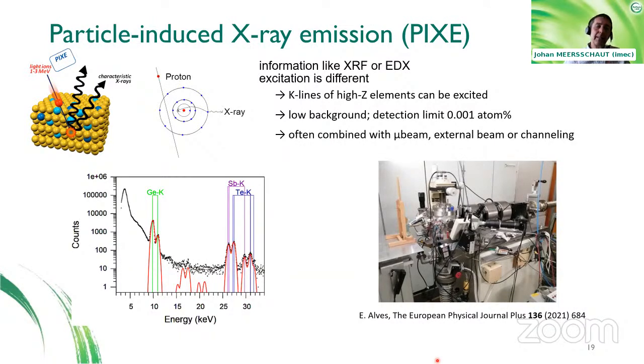For techniques like Rutherford backscattering spectrometry and elastic recoil detection analysis, there are definitely limitations to the sample environment in the sense that the backscattered or emitted particles will be highly decelerated by the environment if they are exposed to, for example, atmospheric pressure. But in the case of particle-induced X-ray emission, we face much less of such a limitation. We are coming in with very light particles like protons that can penetrate several centimeters in air.